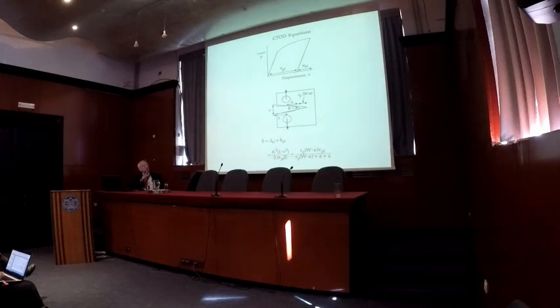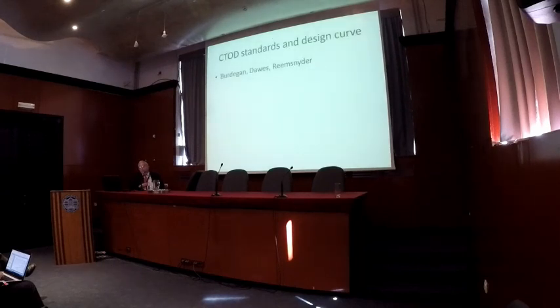but it is an elastic term that is calculated directly from the K. The plastic part is calculated by a rigid plastic model that assumes there is a rigid rotation around a zero stress, zero strain point right here, which is RP times the uncracked width ahead of the crack tip. And then if you measure displacement out here, you use similar triangles or linear extrapolation to get that plastic part. That's CTOD. CTOD has been standardized by ASTM.